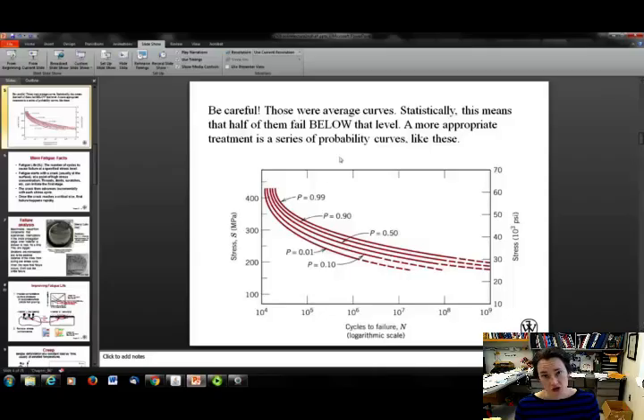Okay, now you have to be really careful, because those curves that I showed were actually average curves. And statistically, what that means is that half of them are going to fail below that level. If that's your mean curve, then half of them are going to fail below that. A more appropriate treatment might be a series of probability curves. And so if you go on and you become a materials engineer, a materials scientist, I would hope that you would do this sort of thing, okay, and plot a parameter and then stay in the safe limit, even for the low probabilities of failure.